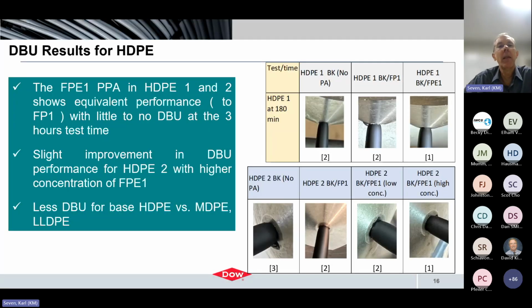We also extended this approach to high density jacketing compounds, and we looked at two different high density base resins, one slightly lower in density, the other, HDPE2, with slightly higher density. With HDPE1, again with no processing aids, we do see some buildup. It's not as severe as what we see with the linear low and the medium density.